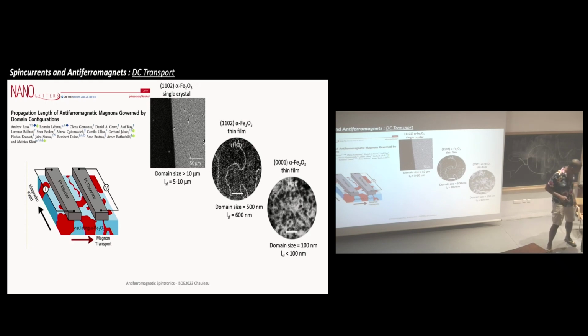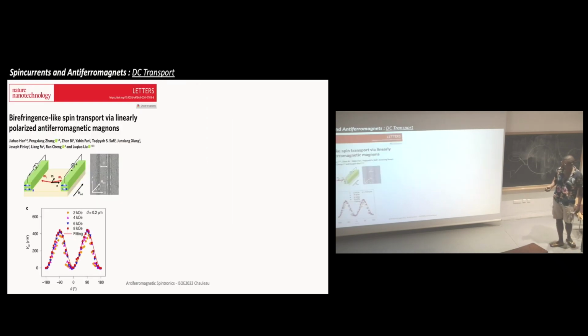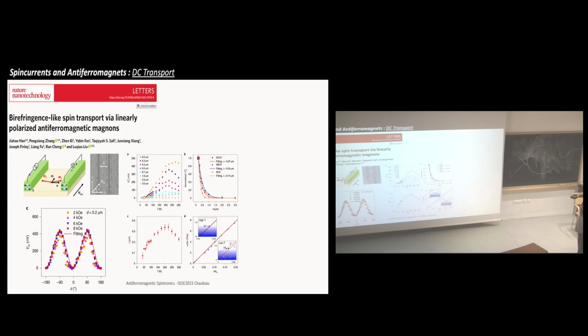But very recently, I would say, there is another very nice paper which also targets this, and they put the finger on something very important, which is why I wanted to advertise it here. They reproduced exactly the same experiment, also in Fe2O3. So you have these two contacts, you excite a spin current, you convey it through the antiferromagnetic material, you pick it up here, and they measure the dependence on the orientation of the field, etc. We can go into detail of this a bit later, but it's not really the point. The point is the following.